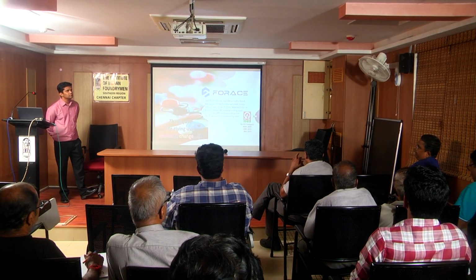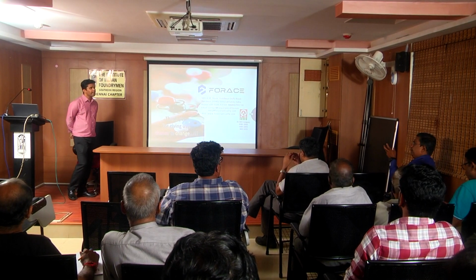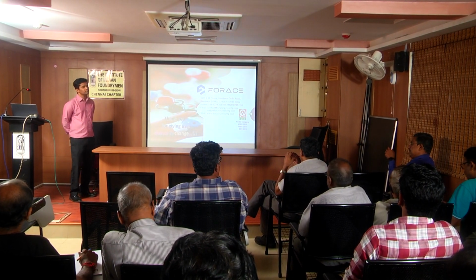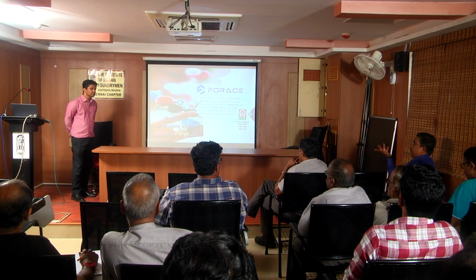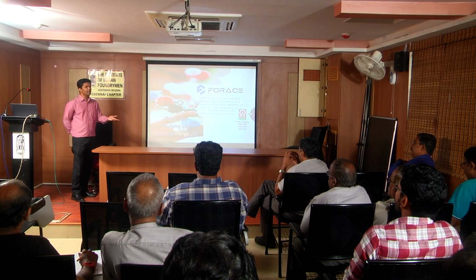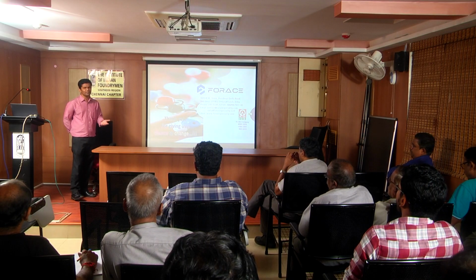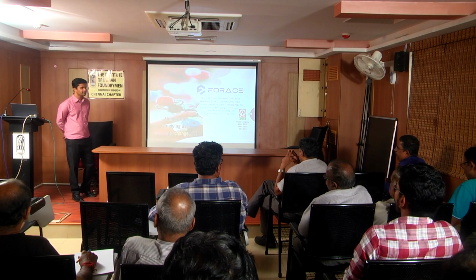Insulating sleeves are recommended for bigger diameter risers. Yes, in a bigger size of riser, the molten metal itself will take a long time to solidify, so there is no need of any exothermic. In terms of MEF, generally it is recommended for insulating sleeves above 6 inches diameter.